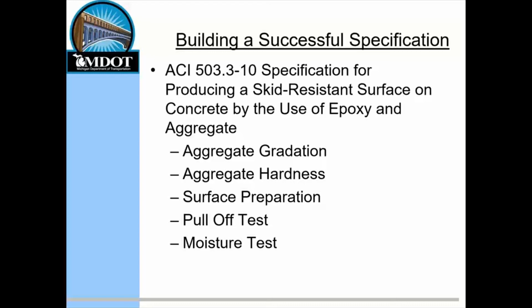The first thing, not listed on here, I want to mention is that we require a 5-year warranty from our contractors on our thin epoxy overlays. That really incentivizes the contractors to do it right and not cut any corners. Because in our experience, if corners are cut, the thin epoxy overlay will fail within the first 2 to 3 years. So if it makes it 5 years without any problem, we know that it was put on correctly, and we're pretty much guaranteed that it's going to last 20 years.